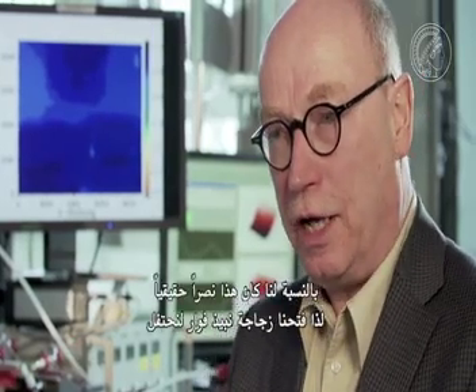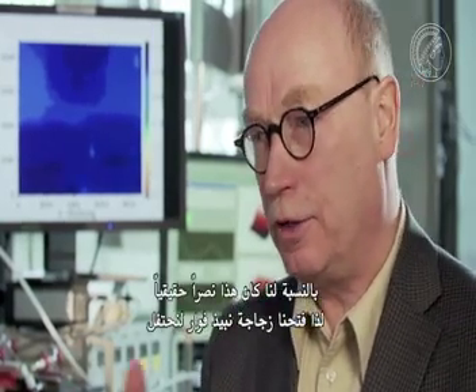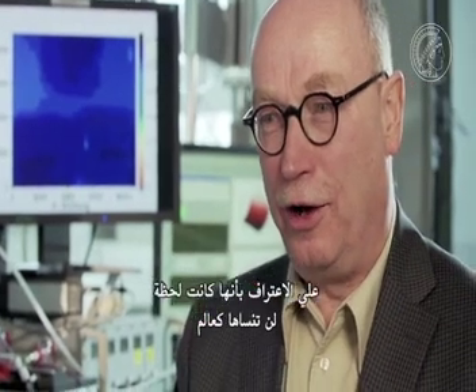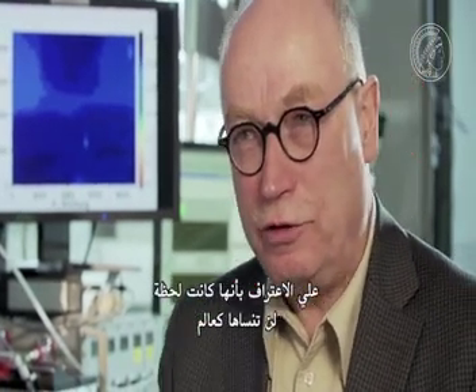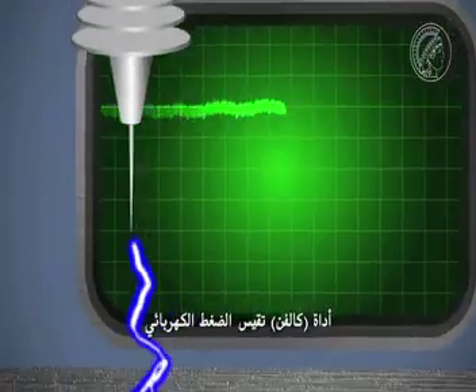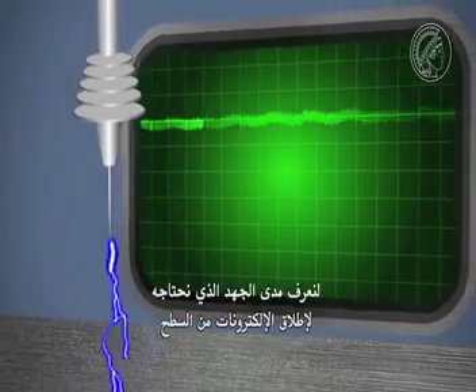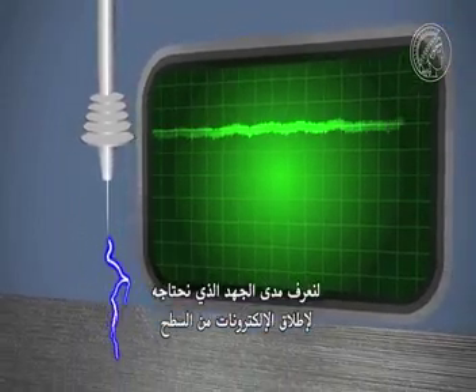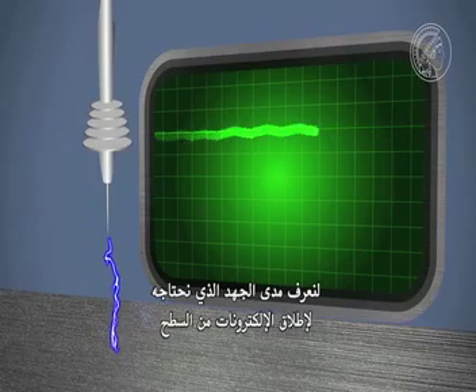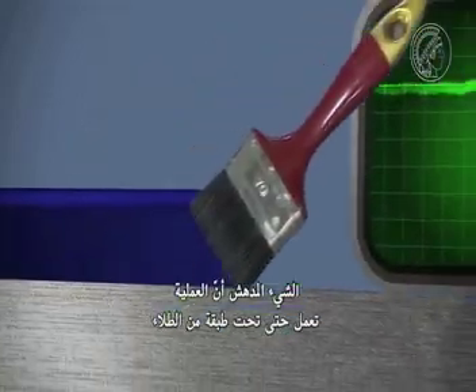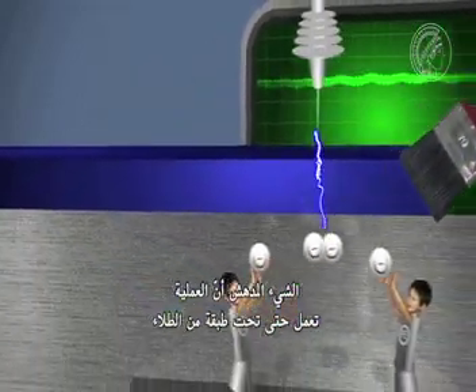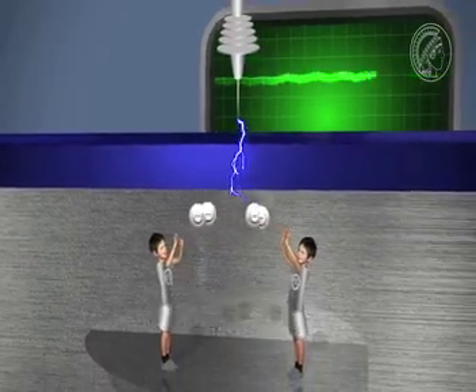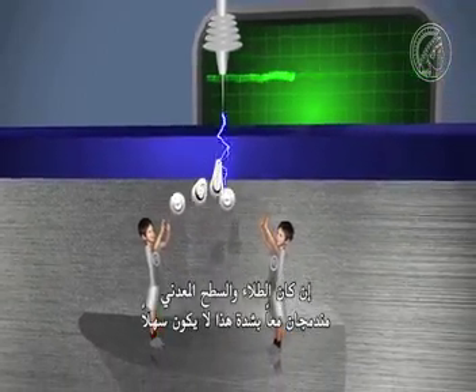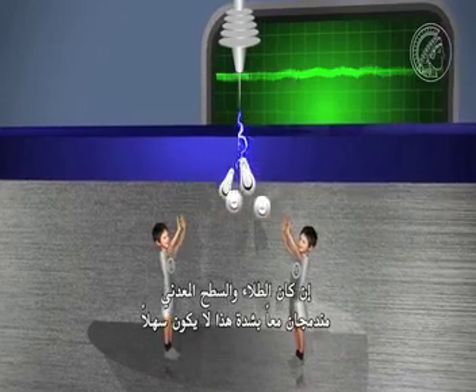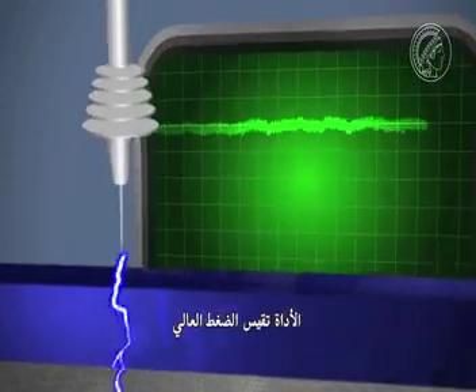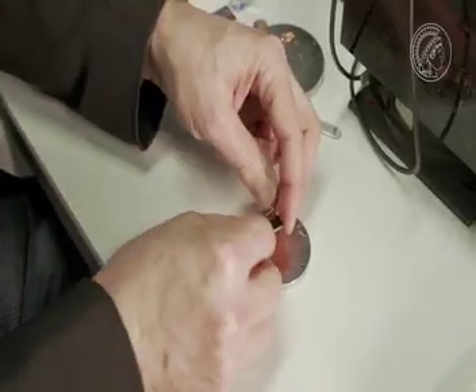For us, that was a real winner, and so we opened a bottle of sparkling wine to celebrate. I must admit that it was a moment that as a scientist you will never forget. The Kelvin probe measures the electrical tension to find out how much effort is necessary to release electrons from a surface. The remarkable thing is that the process functions even through a layer of varnish. If the varnish and metal surface are firmly bonded together, that is not so easy. The probe measures high tension.